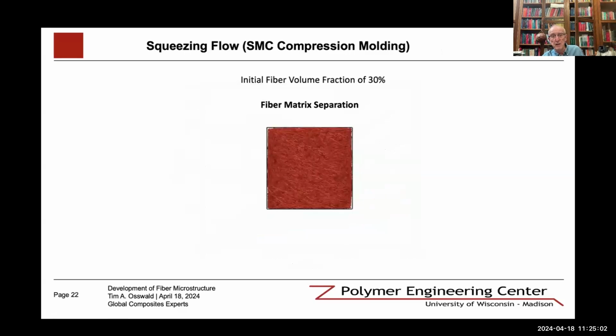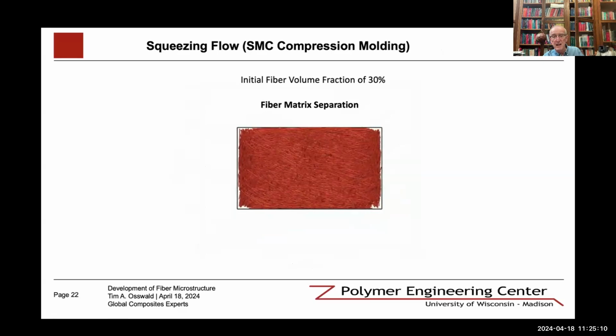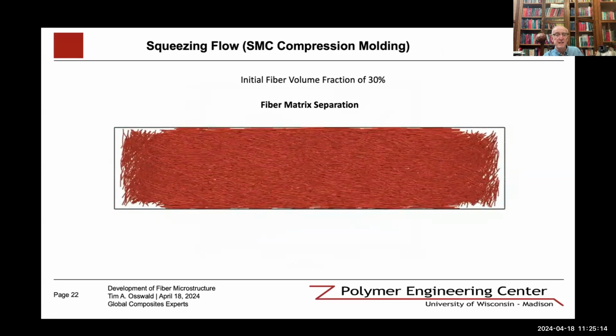If we again look at the compression from the top, we can see fiber matrix separation taking place. The little black box represents the actual volume of the material, and you can see the fibers lagging behind. This is very typical of compression molded parts. If you look at trunk lids and hoods of compression molded parts, the part that first starts failing is the crumbling at the edges. The reason the edges crumble is because they are very poor in fiber content. So this fiber matrix separation is something that we need to deal with and needs to be predicted. It's something that is not quite well understood yet. There are different models by Morris and Boulay and others that represent fiber matrix separation and fiber migration, but they are not quite where they should be.